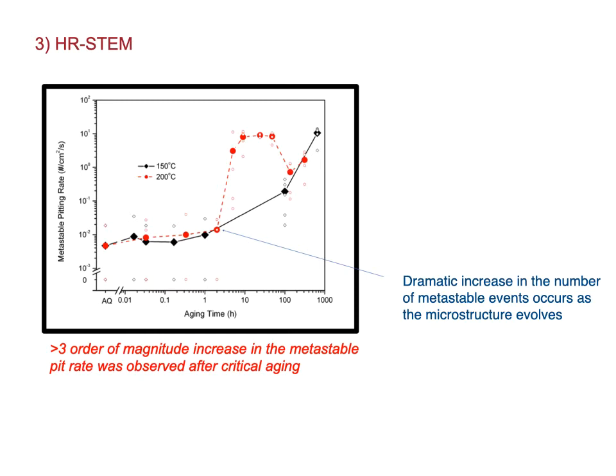So pitting goes from a very low rate to jumping more than 3 orders of magnitude when we age and go from a solutionized alloy to an aged alloy. So what happens to the microstructure to have this jump? You can see the red data points there that correspond to a 200 degree heat treatment, and you see that jump. That jump is brought on earlier than it would be for the 150 degree heat treatment.